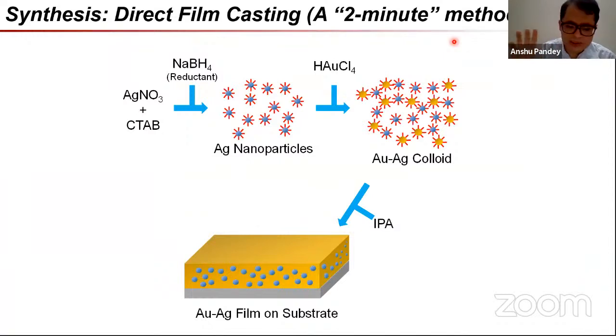This has many caveats because, I would call it a 2-minute method, but 2 minutes is in quotes, because getting to the precursor solution is 2 minutes and then film casting takes a little bit longer. But it is in fact a method which can be implemented rather quickly and allows for a quick verification of the coarser features. So what is done is you essentially start off from silver nitrate and CTAB. These are reduced to produce a silver colloid. Then HAuCl4 is added while the reducing agent is still active. That leads to an AuAg colloid, and that is crashed partially with IPA and deposited to make a film on the substrate. So this is the easy thing which can be done.